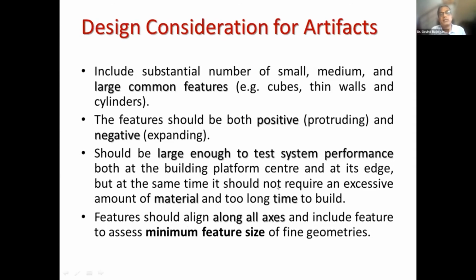So the idea behind this is that we should have a large number of common features so that we can assess the repeatability and the dimensional tolerances. It should have both positive features, that is protrusions, as well as depressions, and it should be large enough that we can get reliable data. Also, it should consume less material and less build time. Also, the features should be oriented in almost all the axes to have assessment based on the direction.